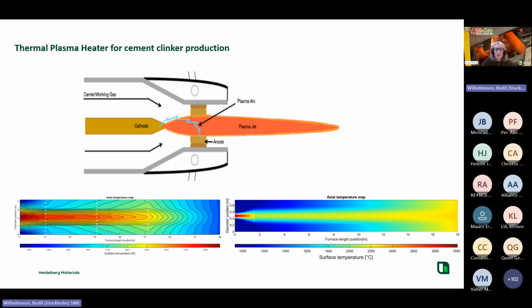So what is happening if we look at a conventional rotary kiln for cement? You see here the temperature along the kiln and the radial temperature. You can see that the high temperature area from a conventional burner is quite long, maybe along half the kiln. But changing this heat technology to a plasma burner with CO2, it will look like this in a theoretical calculation. You see that the temperature is higher, but it's very, very concentrated. It will be quite a small plume.